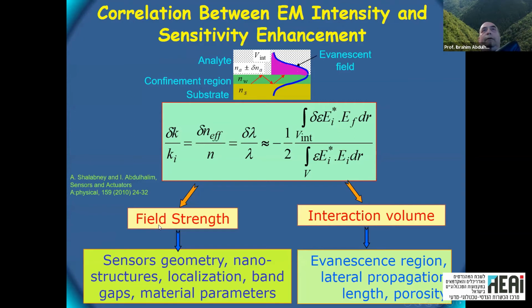So the relation between the field strength and the sensitivity can be seen quite easily if we simply write the wave equation and take the case of a waveguide and say the mode has a k vector, and we look for a very small variation in the refractive index of the waveguide and a small variation of the k vector. Then within what's called first order perturbation theory, you can find that this shift is proportional to the overlap integral between the field before and after introducing the variation in the refractive index, which means it is determined in the end by the strength of the field. So the field strength should give us an indication of the sensitivity.